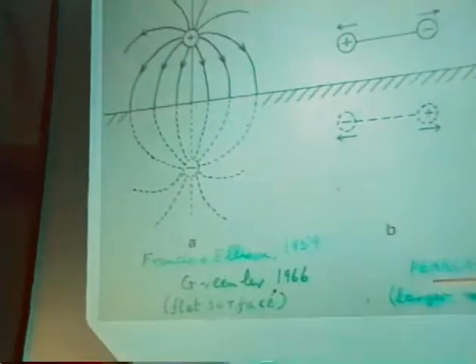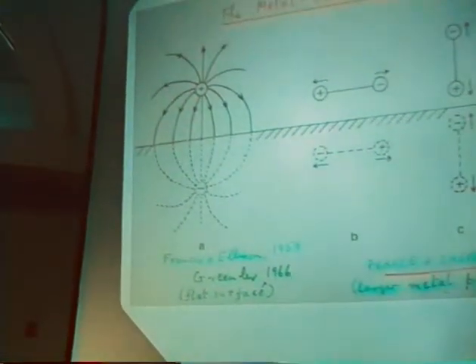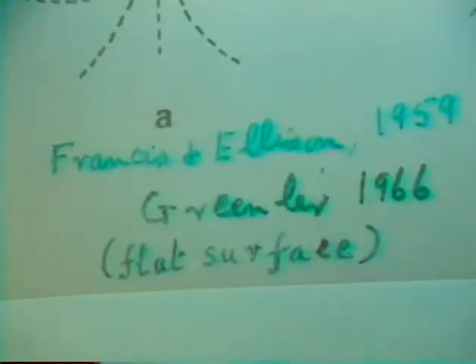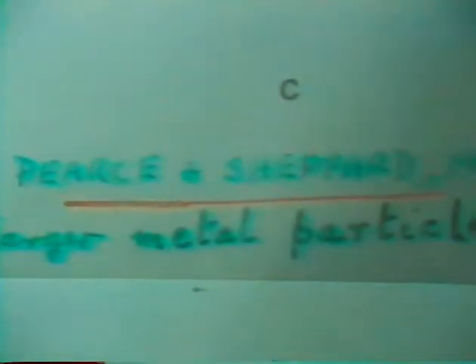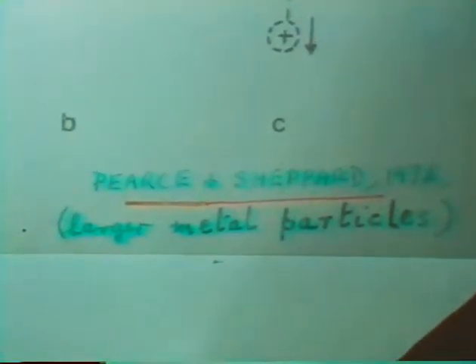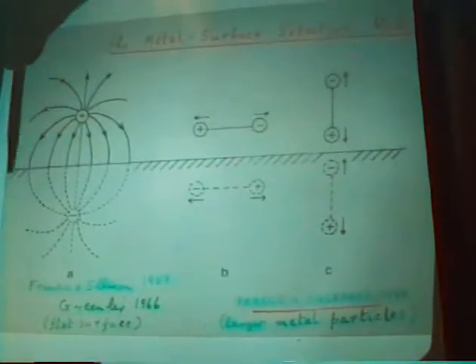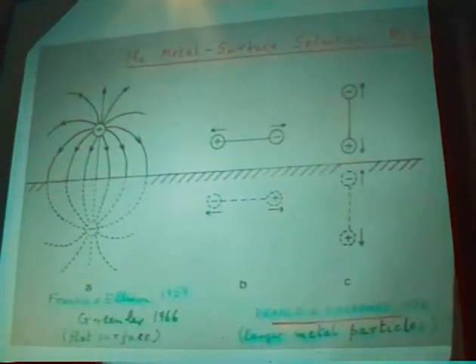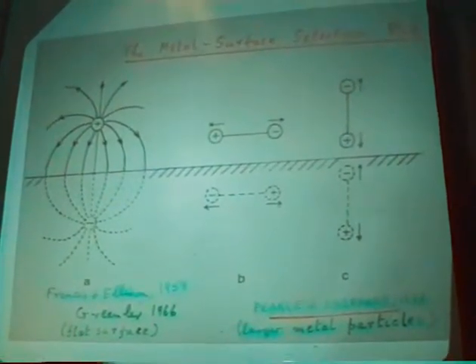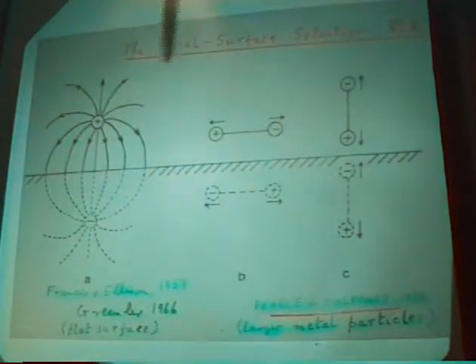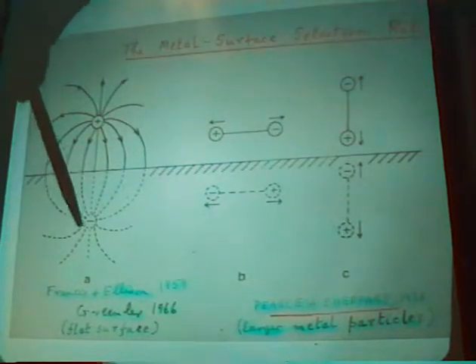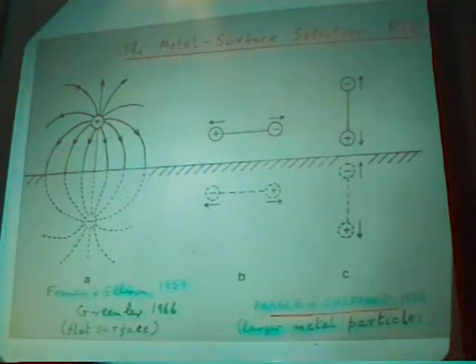Well, the nature of that selection rule can be looked at in various ways, what I sometimes call the physicist's way or the chemist's way. This is the chemist's way, except, of course, it was taught to me by a physics lecturer in Cambridge. If you bring a charge up to a metal surface, then of course the mobile electrons within the metal mean that there's a distribution of negative charge and the lines of force end up perpendicular to the surface. My lecturer at Cambridge said, well, that's the case, but of course the lines of force outside the surface are exactly what they would have been if you didn't have the surface, but you had an equal and opposite, negatively charged image below the surface.